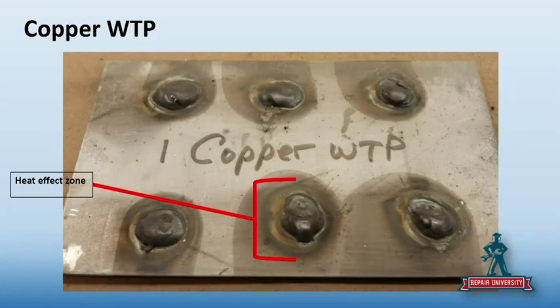And then this is through the copper weld-through primer, where now you can see the heat effect zone is much larger. Yeah. Notice the two on the right there. Those are the ones that are connected, yeah. But look at the first one he started. I mean, you can see that the first one, even that's a bigger footprint than the others, and the halos just get tremendous from there. So that would definitely be a poor weld. We would have overheated our substrates. We would have caused probably damage to the connection panels as well.